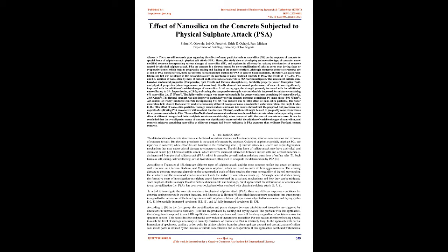Results showed that overall performance of concrete was significantly improved with the addition of variable dosages of nano-silica. At all curing ages, the strength generally increased with the addition of nano-silica up to 6%. In particular, at 28 days of curing, the compressive strength was considerably improved for mixtures containing 6% nano-silica, i.e. 27 N/mm². The split tensile strength was improved especially for concrete mixtures containing 6% nano-silica.